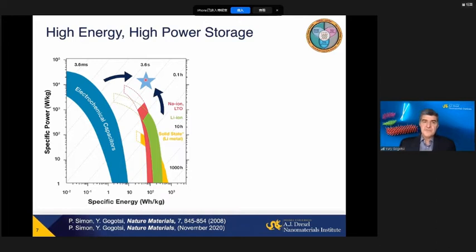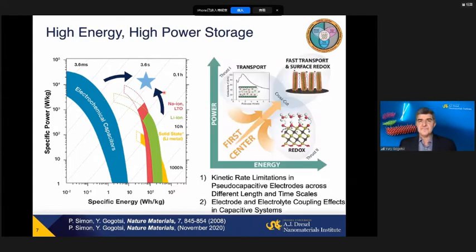Remember that even activated carbon used in electrochemical capacitors has conductivity of, say, tens, maybe 100 millisiemens per centimeter. Actually, very moderate. Graphene and nanotubes go above that, reduced graphene oxide about 2000 siemens per centimeter. MXenes can give you 10 times more, being real metals, having high density of states at the Fermi level.